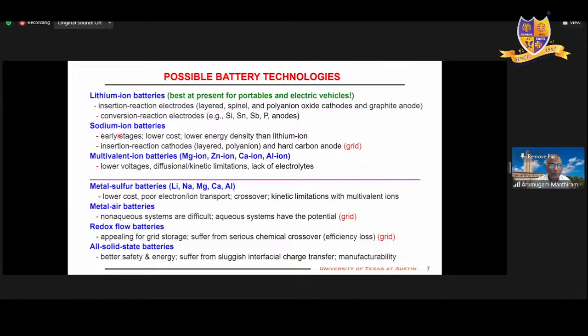And then safety. Cobalt releases oxygen very easily. It's not good for safety. Manganese is better. The polyanions, these X, they will hold the oxygen very tightly. They don't lose oxygen easily. That's the beauty. So the polyanion has the ability to increase the voltage by more than 1 volt, as well as better thermal stability, better safety. That's the beauty. Also, the polyanion concept has a variety of materials, a very broad family.